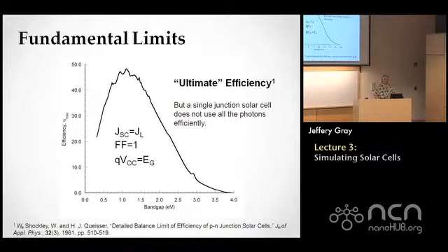But neither one of them uses the photons that it absorbs completely well. Gallium arsenide lets everything with 1.42 eV and less go by, it doesn't use it at all. So that kind of gives you the hint that, well, gee, if I could put another solar cell underneath gallium arsenide that had a lower band gap, I would be able to capture some of that energy back. And that's more or less what we're going to be leading into here in a minute.